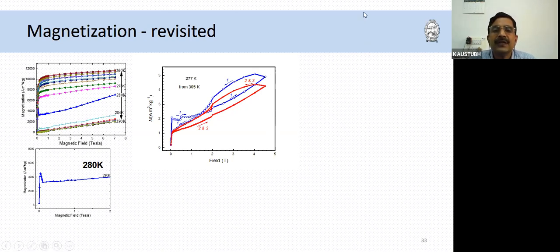And then when we reverse, this is all normal, the magnetization is higher in the reversal phase than in the first cycle. But at some value of field, the magnetization in the reverse cycle becomes lower than the first cycle value, like a magnetization reversal is happening here. But when I bring the field back to zero and go again, I don't get this crossover type of behavior, but I get the normal behavior. If I repeat the cycle again and again, I always get this red curve. I don't get the blue curve. The blue curve comes only the first time, when I cool the sample from above its Curie temperature to the desired temperature. After that, it is always the normal magnetization behavior.